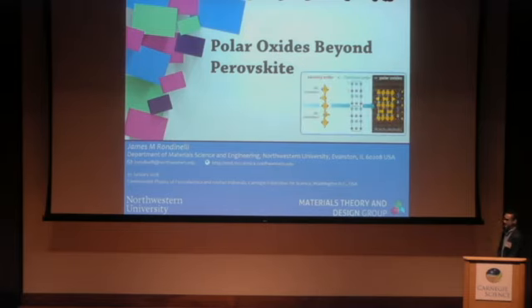The idea I'm going to describe today is shown in this cartoon here, where what I'm going to show you is that you can combine structural vacancy order, so periodic arrangements of multiple polyhedral units, so these are octahedra and tetrahedra, which exhibit long-range order, with cation chemical order to lift inversion symmetry. This is an alternative complementary route to find crystals without inversion symmetry.